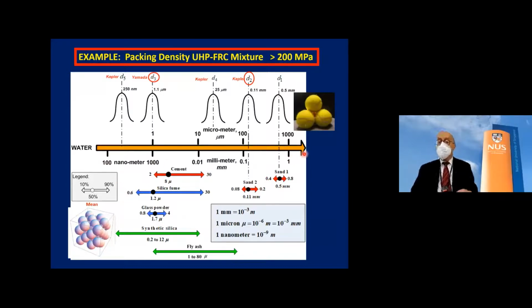This is the size. This is here 1 millimeter or 1,000 micron. In our study, the mix study at the University of Michigan, we selected D1 0.5 millimeter, D2 calculated by Kepler's formula, D3 calculated by Yamada's formula, and we didn't have to use D4, D5 was nanomaterial, so we didn't use that. So eventually we used 3 different diameters of particle. This is our sand 1, this is our sand 2, cement, silica fume were able to produce the D3, and glass powder, the D3. Now, the green things here, we didn't use them, but I put them to show that if we needed different diameters, we could have managed that as well.